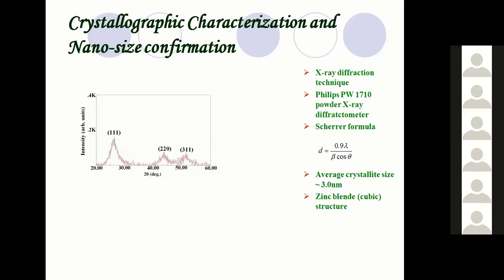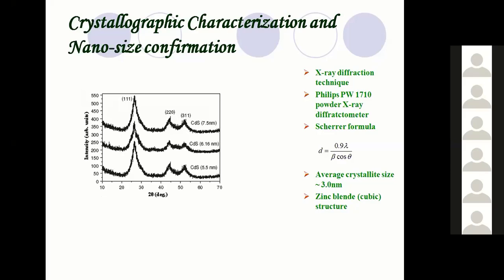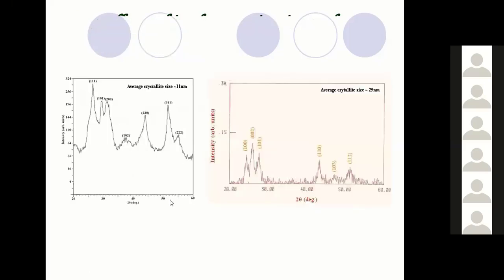Here, this is the diffraction pattern which was recorded for cadmium sulfide. It has been seen that in this case, the structure of the cadmium sulfide was zinc blende and the average crystallite size was 3 nanometer. We have recorded the diffraction pattern for different sized nanoparticles of the cadmium sulfide. It has been seen that when the size went on reducing from 7.5 nanometer to 5.5 nanometer, the broadening in the XRD pattern went on increasing. So with the decrease in the particle size, the peak broadening takes place.